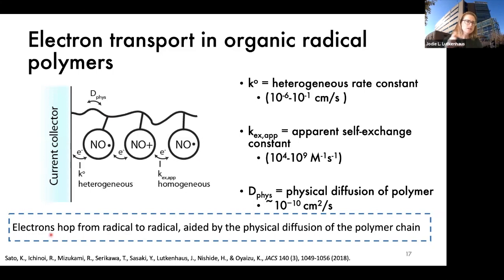So basically the electrons are hopping from radical to radical. That was already assumed and not new news. But the new feature that he added was that physical diffusion of the polymer chain is a really major part of how the electrons can hop from group to group. So before this, models had been assuming that the radical groups were kind of frozen in place, but really we need to remember polymers have some segmental mobility, and so these spheres, if you can imagine, can knock against each other once in a while as the polymer is wiggling around, and that's going to contribute to how the electron